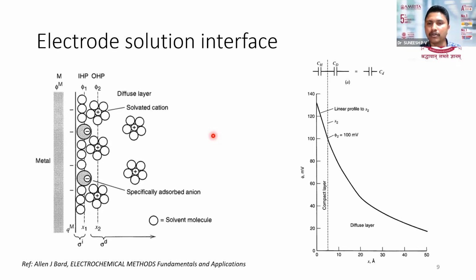In between, water or other solvent can be trapped, and thereby it acts similar to a parallel plate capacitor, where you have two charged plates and in between them a dielectric. And this generates a potential on the electrode surface. When we apply a potential to charge the capacitor, these ions will specifically adsorb on the surface, and that will generate the capacitance. So the more ions sticking on or adsorbing on the surface, the more capacitance we get. And when we move towards the bulk of the solution, this charge accumulation decreases.